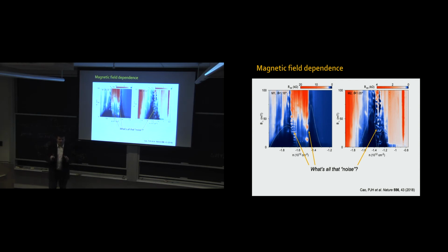What happens is you have a two-dimensional superconductor that you're switching between superconductor and insulator. So if you tune your chemical potential in between, what does it do? Does it become superconductor or insulator? Well, it does both—it segregates into islands which are superconducting and insulator.